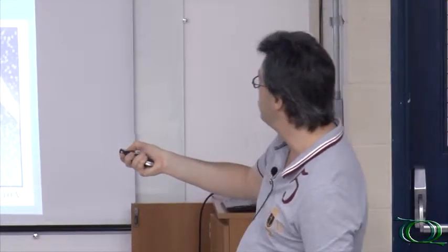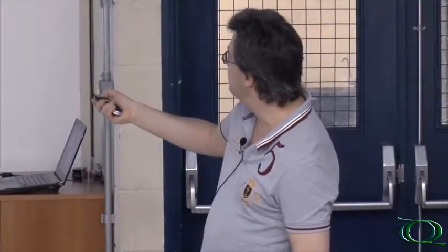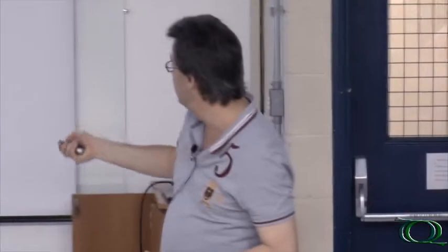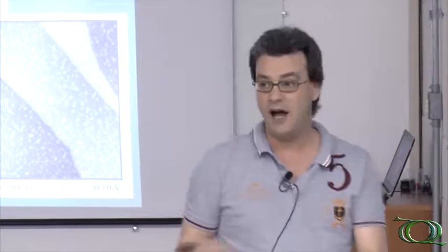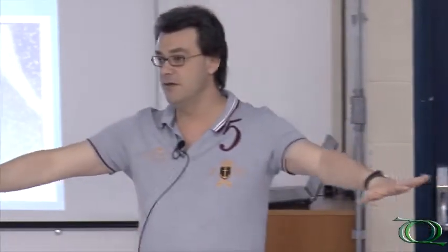And when we look at this with the STM, we see this thing here, which looks very similar to this. The only difference is these big islands here. We know that these big islands are copper that has gone underneath. So the system here is not so perfect as this one, because some of the copper goes underneath the cyanide, but we still are making very tiny islands and making sandwich structures. And the interesting thing is that here the islands are much more similar in size than here. And this is probably due to the particular structure of the cyanide-modified platinum 111 surface.